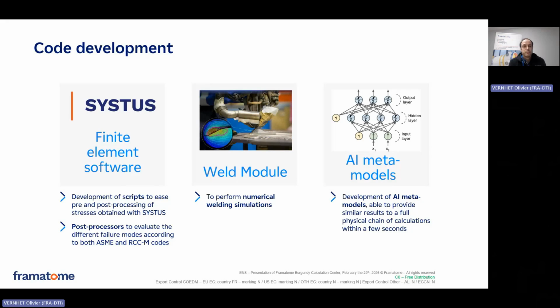And we also develop post-processors, which are, let's say, plugins that go just after SYSTUS, take into account the stresses that are the output of SYSTUS calculations, and then provide stress intensity factors when we study fast fracture, cumulative usage factor when we study fatigue, for example, or membrane stresses when we study excessive deformation. So we have developed all those post-processors that are compliant with RCCM, with ASME, or with different codes and standards to get the criteria required by the different codes.